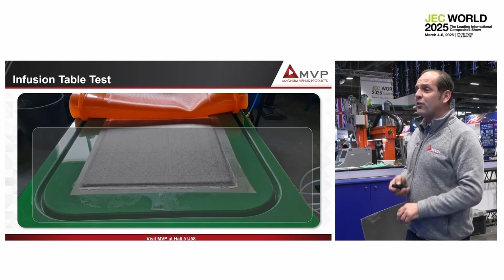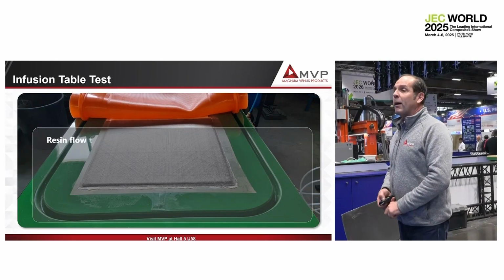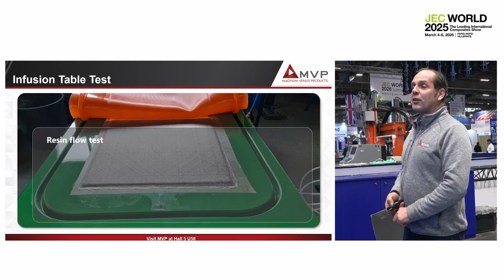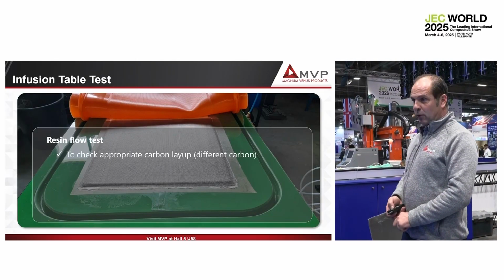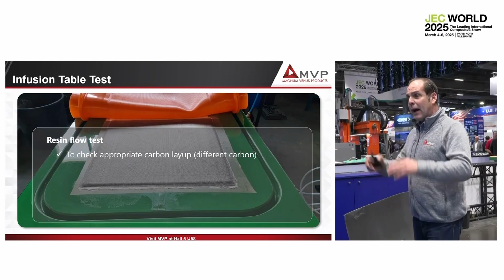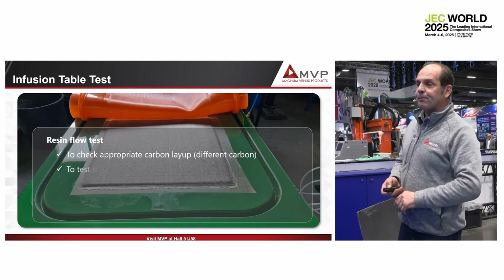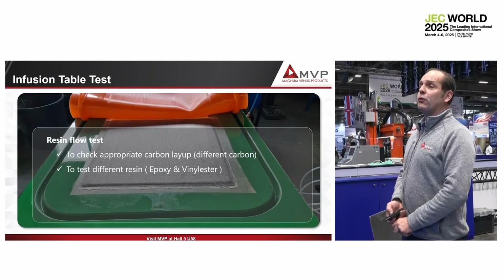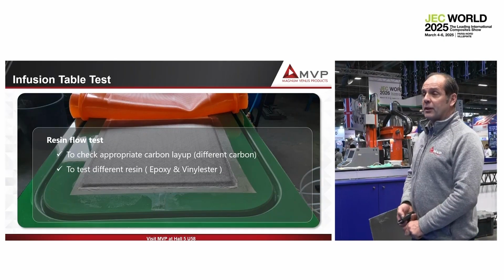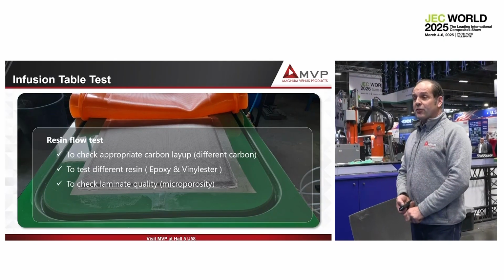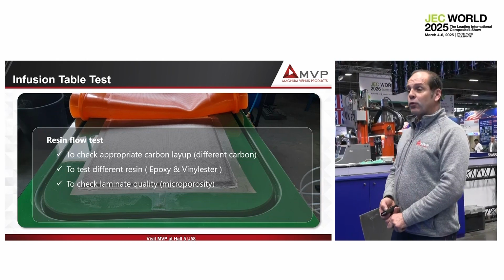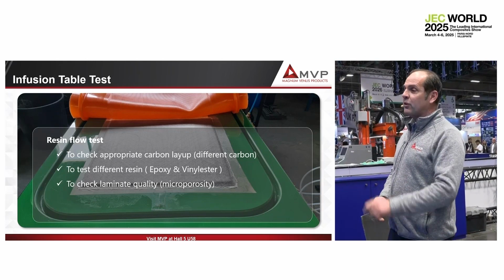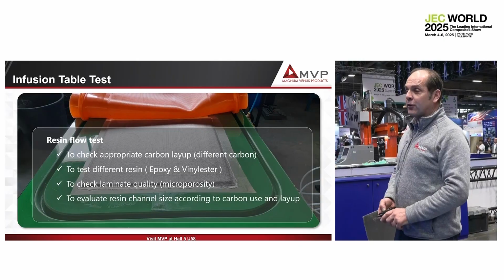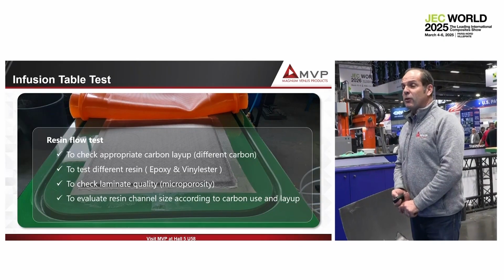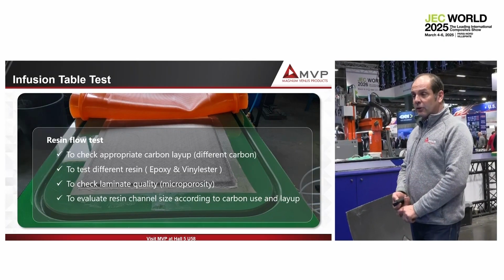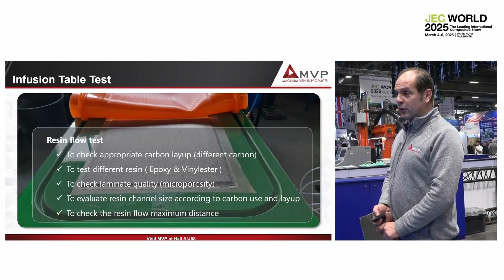So that's why we decided to help the resin flow by grooving the silicone membrane. We have different kinds of groove according to the resin viscosity. So we do the infusion table test to check the appropriate carbon layup, to test different resins, epoxy, vinyl ester, to check the laminate quality, microporosity, fiber content, and so on, and to evaluate the resin channel size according to the layup and the resin viscosity.